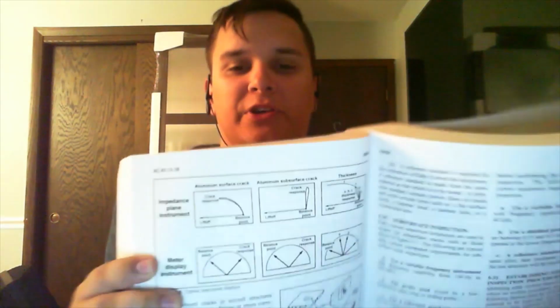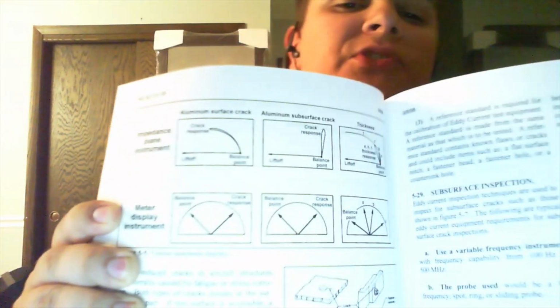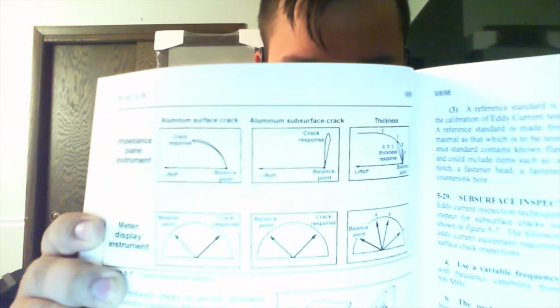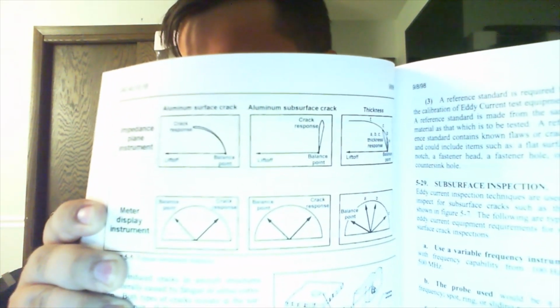Now, I have a picture of this because it's easy to explain, but it's nicer with a picture. If you look at this, you see the balance points of the actual material. Once the balance points are used on the material, the actual readings will come back. Once the readings come back, it's easier to determine what's wrong with it, like the thickness, the balance point, the crack response. If it's somewhere in the middle, there's a crack. If it's somewhere on the outside or even close to the outside, there's still a crack because it's not fully off to the side. Now, if the crack is deep enough where it's noticeable, of course, you're using visual inspection. But with eddy current, you can actually detect the thickness, and if the thickness gets smaller, bigger and bigger on the edge of it, you know there's something wrong.